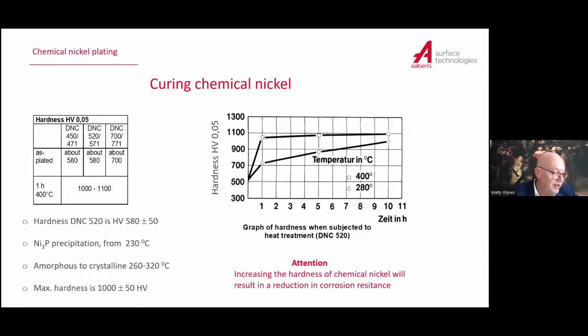Then that chemical nickel, you can cure that. And just as I told you, you can temper it and make it harder. When you look here on the left side, the normal hardness of the chemical nickel, DNC is the brand name which we use, is just about 580 hardness figures. When you heat it up in an oven, after 230 degrees, you get precipitation forming in the system, in the layer. And after 260 degrees, it starts getting crystalline, turning the amorphous system into a crystalline system. And that raises the hardness then to 1,000 hardness figures.